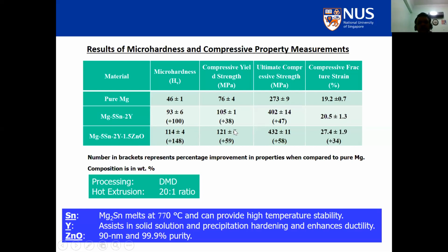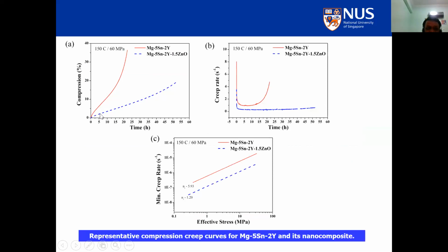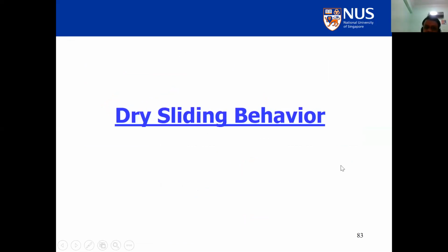Again, we see an increase in the strength levels. And the ductility is 27.4, much higher than aluminum alloys that you can think of. So that's a magic again of the nanoparticles. So we gave them this material and they did the creep studies, and you see the blue curve corresponds to the nanocomposite and is always better than that of the monolithic material. So that means the creep response of the nanocomposite is superior to that of the monolithic material.